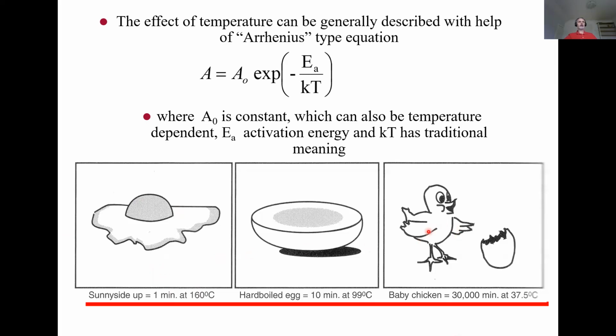So this is here just to show that these equations, whenever they contain these parts, are valid only in a certain temperature range. If you go outside that temperature range, the failure mechanism is changed, and then the results they are giving can be roughly correct, roughly wrong, or complete rubbish, like here.